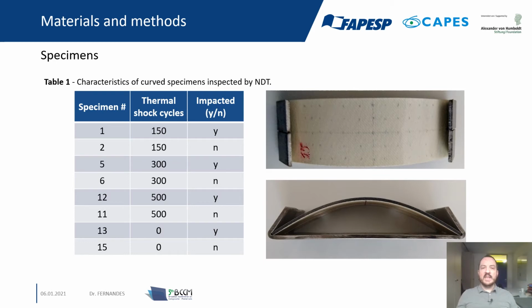So we had 8 samples, with 4 different thermal shock cycle conditions: 0, 150, 300, and 500. And here on the right we have an example of specimen number 15, which was not subject to thermal shock cycles nor impact.